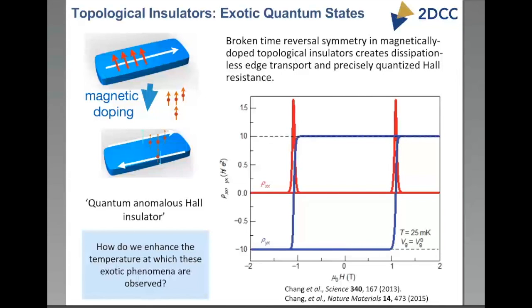You might wonder why we're interested in these magnetically doped films. It turns out that by magnetically doping topological insulators, we can get these exotic states, which are called quantum anomalous Hall insulators. This is a problem we are deeply interested in, and we are interested in figuring out how we enhance the temperatures at which these exotic phenomena are observed. Currently, you need a low temperature dilution fridge or a helium-3 cryostat to see these kinds of phenomena. And what this plot here shows is that if you take a topological insulator, dope it with, in this case, vanadium, this is work that was done as a collaboration between a group at Penn State and a group at MIT. Then the Hall resistance is precisely quantized, and the longitudinal resistance is dissipationless. It goes to 0.